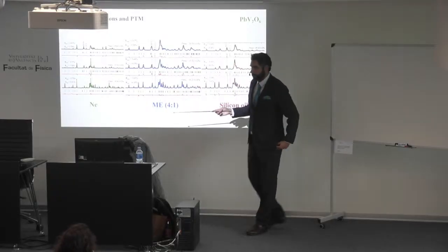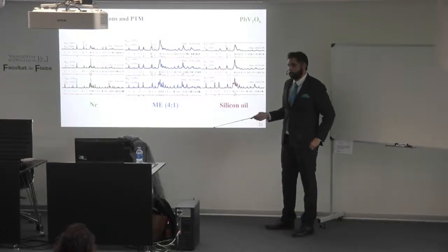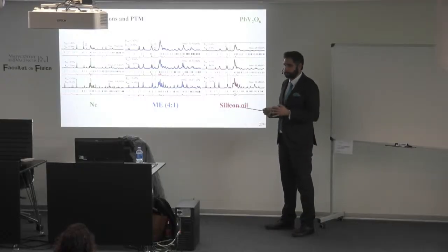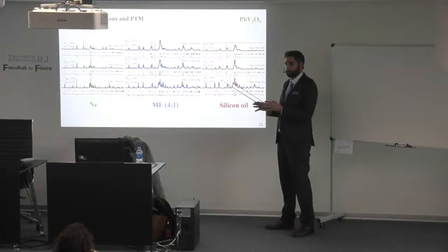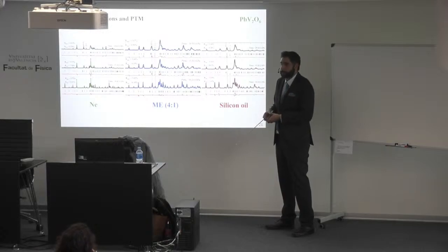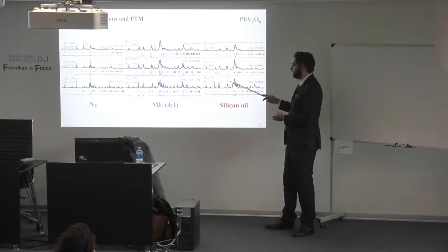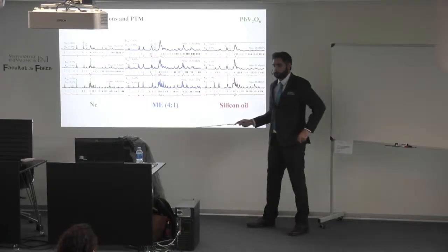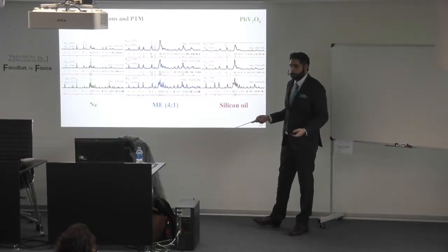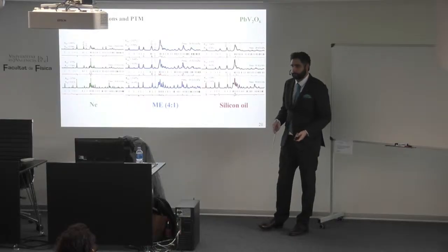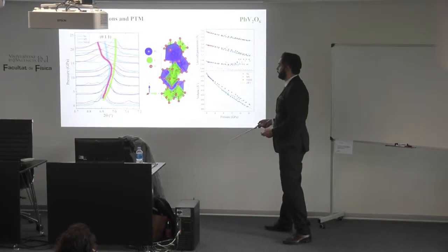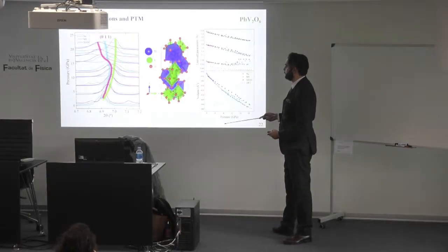So what does it mean? When you are doing high pressure experiments, you expect the diffraction peaks to go to the right, because this means that the structure or the lattice parameters are shrinking, collapsing due to the pressure. But in this case, they did something that was not expected. So we said, okay, we have to investigate if this is a phase transition or what's going on here. In this case, the animation is not working, but well.